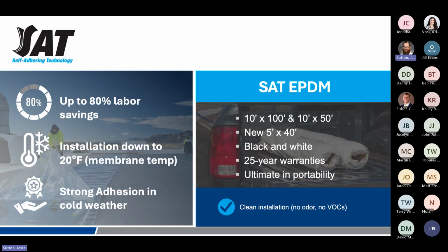And our SAT EPDM, actually, you can install down to 20 degrees. It's somewhat important to note that that's the membrane temperature. If you're really checking the temperature and it does get close to 20 degrees, just keep an eye on that. It does lose tack below that, and we've seen poor performance under 20 degrees. So it is important to check your membrane temperature with an infrared gun and just make sure you're above that 20-degree mark.